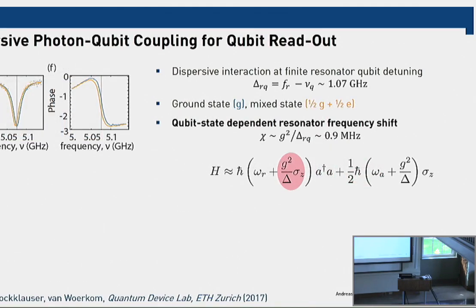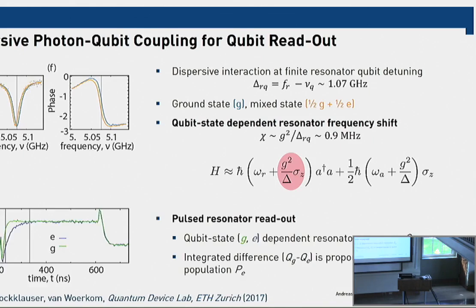So here's a cavity spectrum with the qubit in the ground state, which is shown in blue, and the qubit in a mixed state in orange. And you see that the cavity frequency shifts a little bit, and you could also measure the phase, and you see that the phase profile shifts a little bit. And you could do a time-resolved measurement where around this time you prepare the qubit either in the excited state or in the ground state, and you look at when you apply a microwave pulse to your cavity how the pulsed response varies depending on the state of the qubit, either in the excited or the ground state. And the difference in these two responses then allows you to perform a time-resolved measurement of the charge state in the quantum dot.